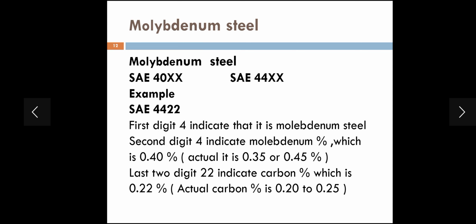Now next is molybdenum steel. Please note, maximum molybdenum in any steel is never more than 1%. Maximum is 1%. Because of moly, it increases the hardenability at elevated temperature and improves corrosion resistance. An example of moly steel is SAE 4422. The first 4 indicates the type of steel, so 4 is a molybdenum steel. The second 4 indicates moly percentage as the principal element in the steel, 0.4% moly. And the last two digits 22 are the carbon percentage, 0.22% of carbon.